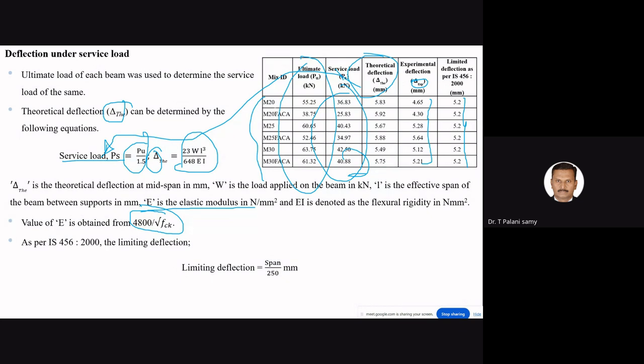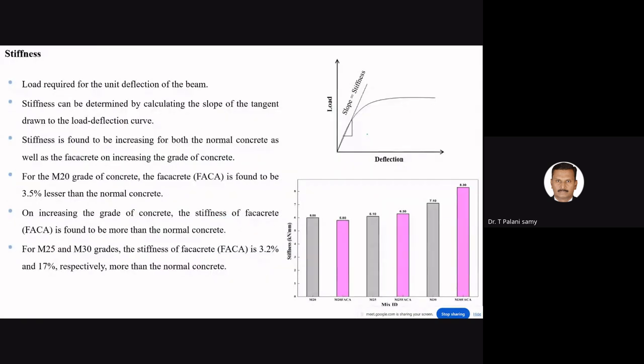For example, for M20 grade concrete, the theoretical deflection is 5.83, the experimental deflection is 4.65, and the limiting deflection is 5.2. So the theoretical deflection is slightly greater than the limiting deflection, but the experimental deflection, 4.65, is within the limiting value of 5.2. Similarly, you can observe the same trend in all other specimens. So likewise, we can ensure our concrete specimen is good for the limiting deflection, and also more or less aligned with the theoretical deflection when compared to the experimental deflections, and on par with the limiting deflection suggested by IS 456 2000. Then another very important phenomenon is stiffness.